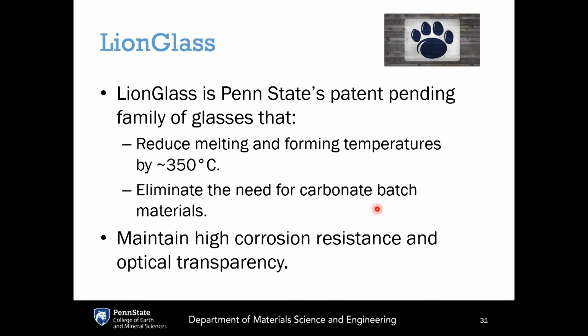So this is our patent-pending family of glasses that is meant to be a replacement for traditional soda lime silicate glasses. So it's meant to directly address this issue of the carbon footprint of the glass industry by reducing the melting and forming temperatures by on the order of 350 degrees C, which is substantial savings in energy. And it's made from a chemistry that also, in parallel, eliminates the need for carbonate batch materials. So that part of the carbon emission is eliminated. The other part is greatly reduced.